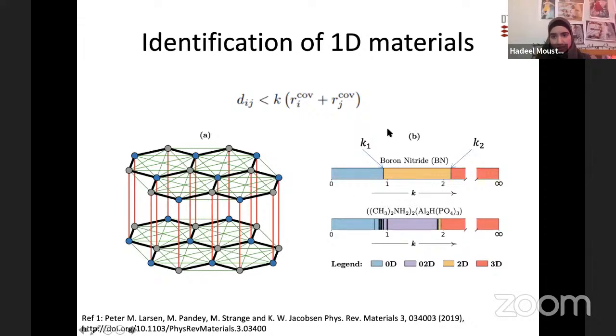So if we take an example here and look at boron nitride, then at a low value of K, we have a 0-dimensional material. Then at K1, the covalent bonds begin to set up between the atoms, and then we are dealing with a 2D material. And then at K2, the red line appears between the layers, and then we are dealing with a 3D component.